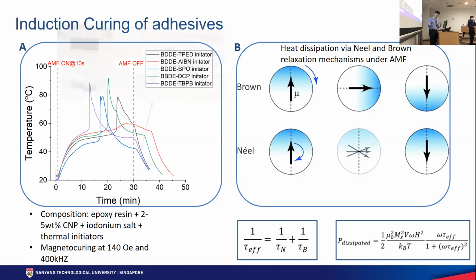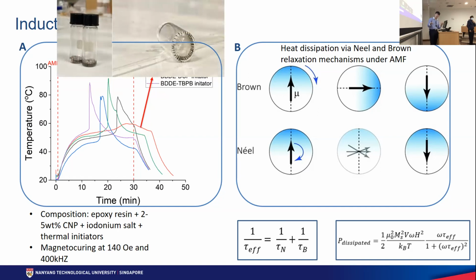And when that happens, we obtain this curing profile. So the adhesive turns from a transparent liquid into a transparent solid over here. And as you can see, these nanoparticles are locked into these cured adhesive matrices. Very stable.